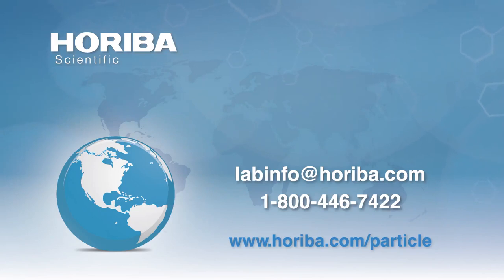That's where you're going to need a particle size analyzer. There are some paint companies that have particle size analyzers. There are some that have very stable TiO2. You can take the TiO2, independent of concentration, and determine from day one to 20 years from now that you'll have the same GSD, the same particle size distribution. You take that and you determine whether the additives, the rheology modifiers, the resin itself, is increasing or decreasing the particle size.